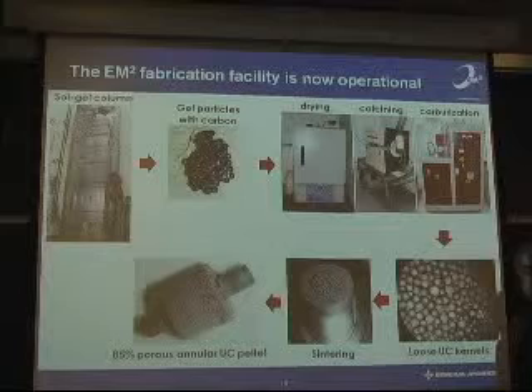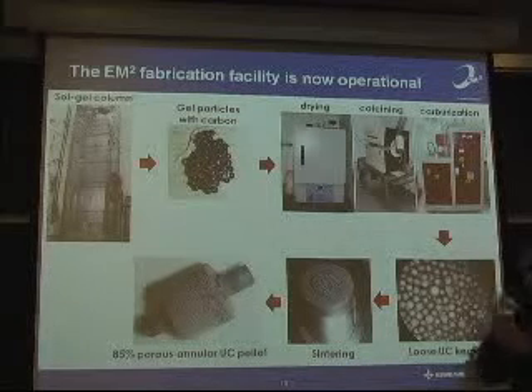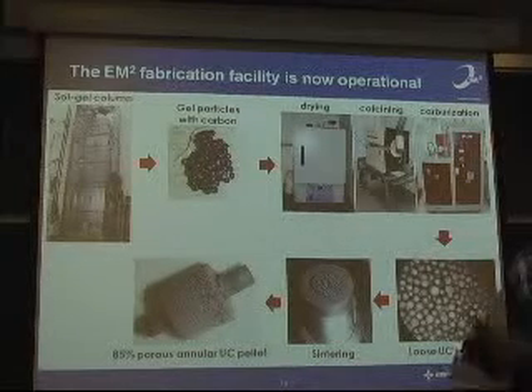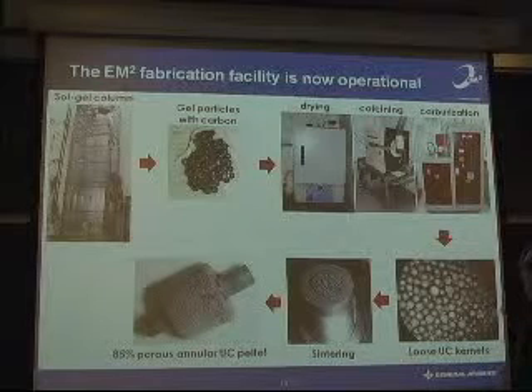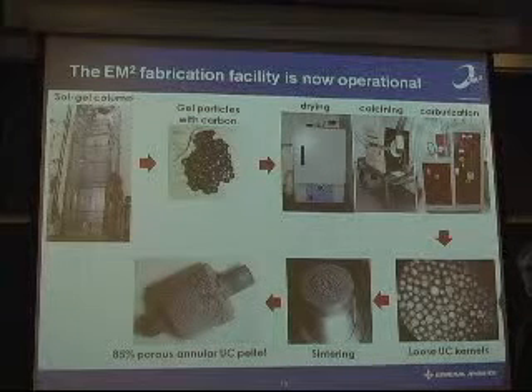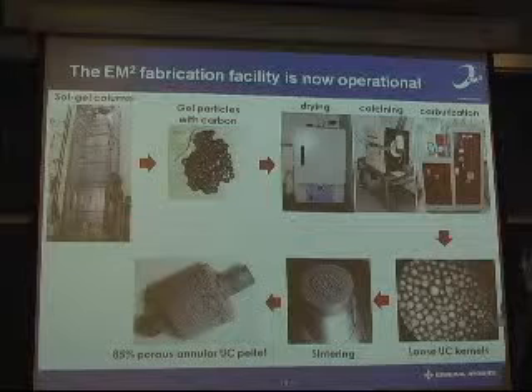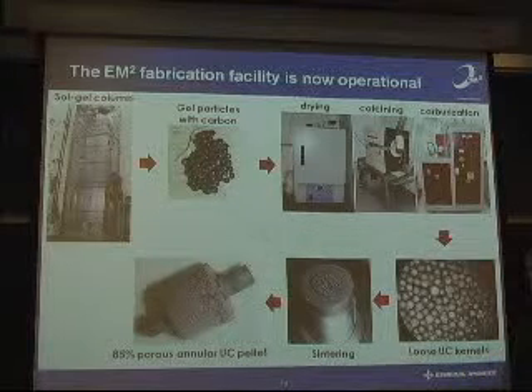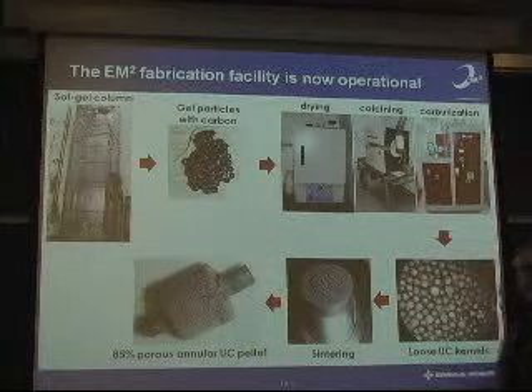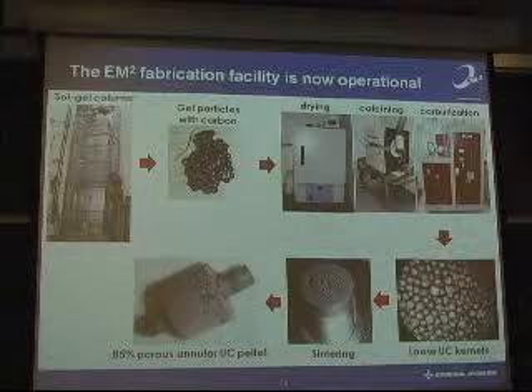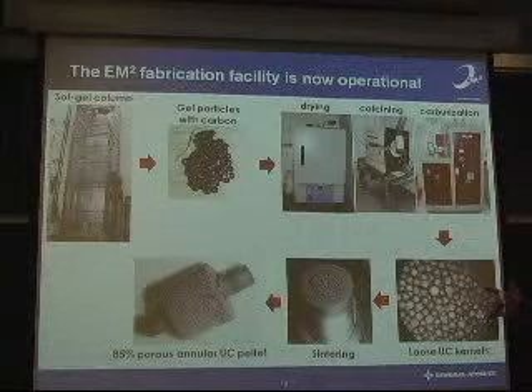It's not monocarbide. We have to add a little extra carbon in there because fission products like to grab carbon. And we don't want it grabbing carbon from the silicon carbide composite clad. So we have to put a little extra carbon there to be sure that we passivate those fission products. So we make these UC kernels, and then we sinter them.